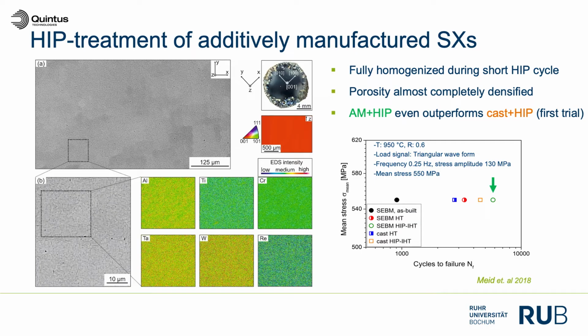It's for sure. And the very interesting part is here that we also developed a very short heat treatment in the HIP for this class of materials, because everything is much finer. You can also shorten the heat treatment time. And here we have developed a very efficient heat treatment in the HIP, integrated, which takes about 45 minutes of holding time in comparison to 8 hours for a casting material, which is impressive.